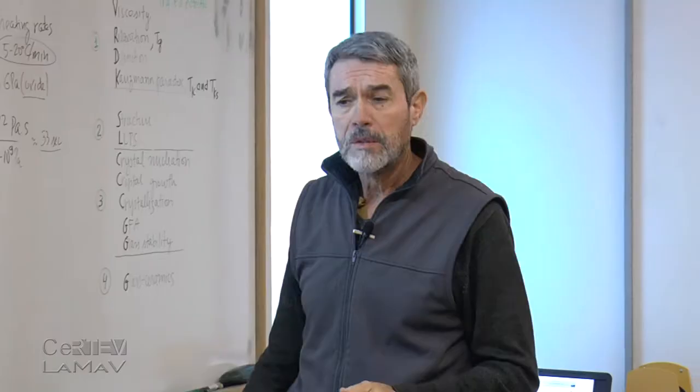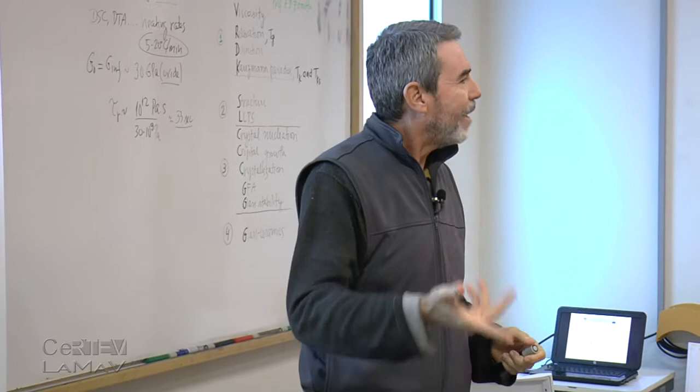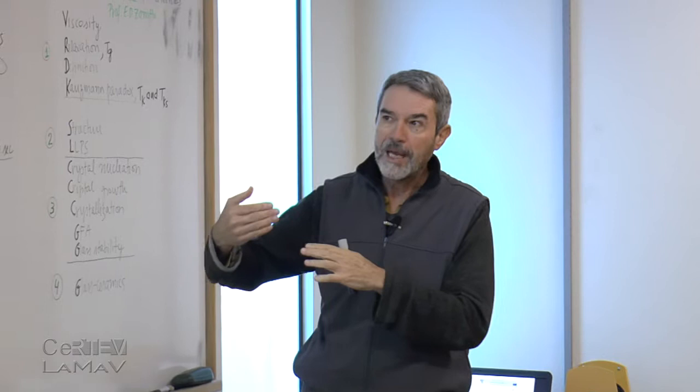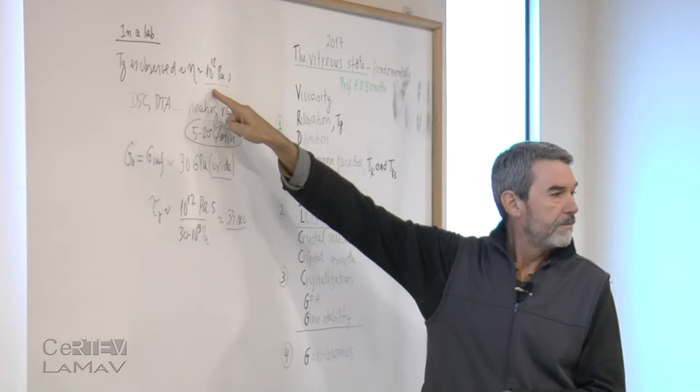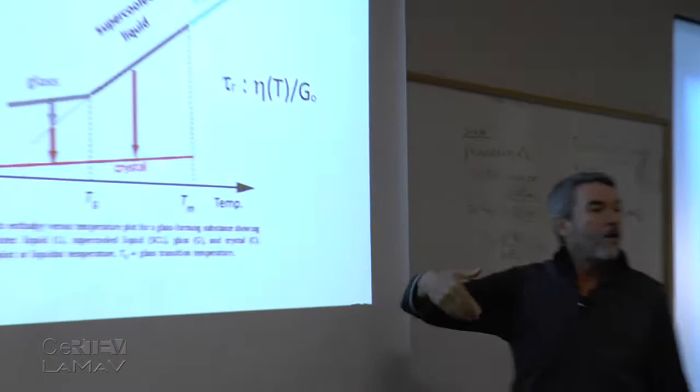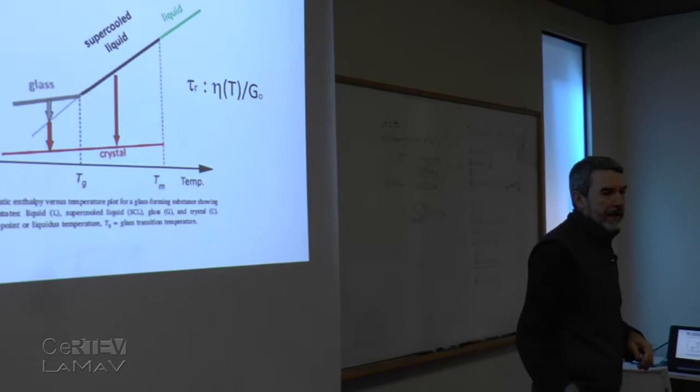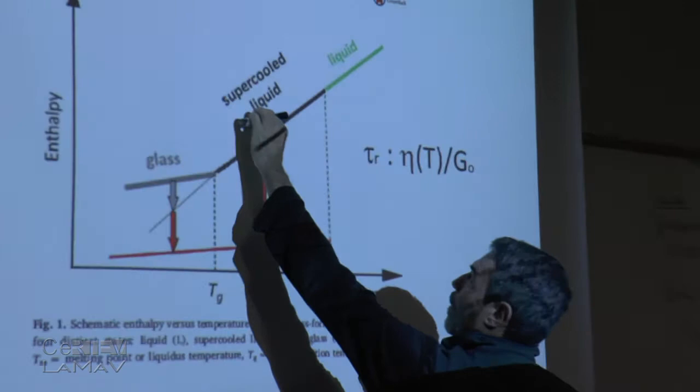If you use much higher heating rates, there are now DSCs that can go to 10,000 degrees Celsius per minute. We have one in the lab that goes to 1,000, but there is newer equipment that can go much higher. Then the Tg will take place where the viscosity is lower. Or if we measure Tg by molecular dynamics simulations, which have extremely high cooling rates, then Tg would be somewhere here, where the viscosity is maybe 10 to the 6 or 10 to the 5 Pascal second.